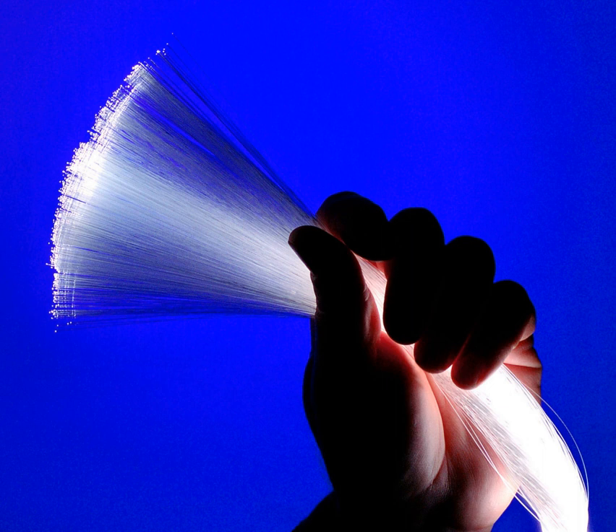At high optical intensities, above 2 MW per square centimeter, when a fiber is subjected to a shock or is otherwise suddenly damaged, a fiber fuse can occur. The reflection from the damage vaporizes the fiber immediately before the break, and this new defect remains reflective so that the damage propagates back toward the transmitter at 1–3 meters per second. The open fiber control system, which ensures laser eye safety in the event of a broken fiber, can also effectively halt propagation of the fiber fuse. In situations, such as undersea cables, where high power levels might be used without the need for open fiber control, a fiber fuse protection device at the transmitter can break the circuit to keep damage to a minimum.